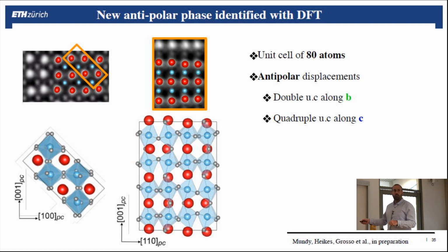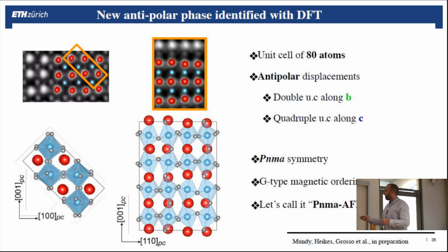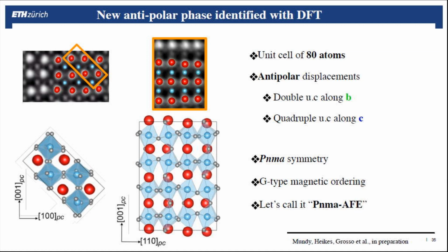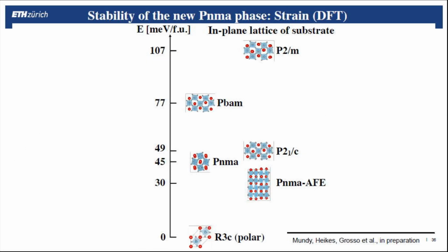And the way that we were sure that this was the correct structure was by taking these structures and simulating these images. And you see that there is a perfect match. The symmetry of this is called PNMA. It doesn't matter so much here. Just know that it's a non-polar phase, or a centrosymmetric structure. It is still G-type, so that means that the spins are out of plane and in plane in opposite directions. And let's call this one PNMA antiferroelectric for a reason that will become clear.